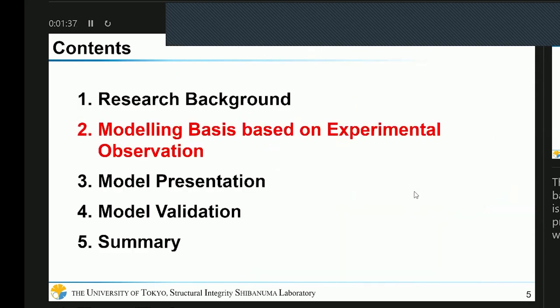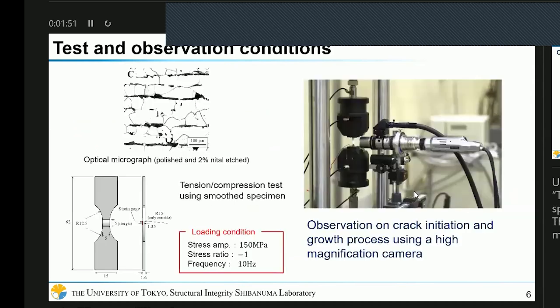So next, I will show you the modeling basis based on experimental observation, which is the most important part of this presentation, though it's not numerical work, but experimental work. This slide shows the test and observation conditions. Using an ordinary ferrite-pearlite steel, we performed a tension-compression test using a smooth specimen like this. And we observed the crack initiation and growth process using a high magnification camera.